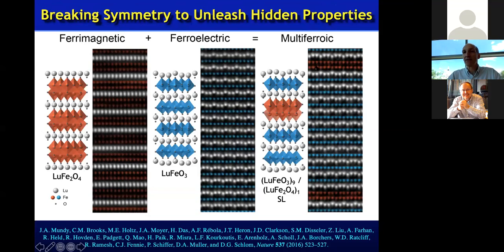But if you look down here, ferroelectric. Exactly. So if you look, there are domain walls vertically in the structure, and they lie here, and they also lie in the middle of this part. Here, if you look at the top of this block, it's two down, one up. Mm-hmm. And here it's two up, one down. Oh, I see. Okay. So there's a domain wall here, and there's a domain wall there. And I didn't put it in the talk, but Megan has mapped 200,000 columns now in these structures to map out the domain wall distribution and look at the statistics.